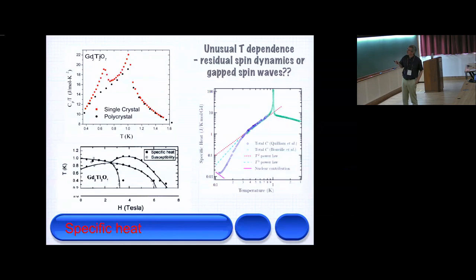And depending on how low in temperature you can get your data, so the green was first, you can say this is nice and linear. You can do some of the modeling that was discussed earlier, and you say there's a lot of degeneracy, it's gapped, it's not gapped, whatnot. If you're able to get more data, then you can reduce the number of models. And then in this system, you have to worry about a nuclear contribution for this small little upturn. But now we believe, if we just had this, the first paper that was published said it had residual spin dynamics. The second, no, this is the titanate and this is the stannate. And so when we saw the stannate with only one transition, we thought Palmer-Chalker might be correct, but we've done the measurements on both.